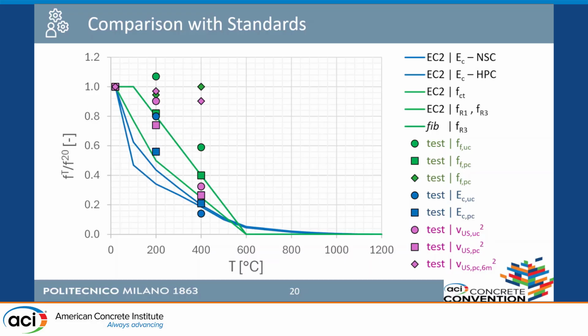I hope in the future to focus also on this aspect, because before 450 degrees C, during the curing after fire, we have a recovery thanks to the rehydration of the anhydrated particles and to the precipitation of calcium carbonate. After 450 degrees C, or even more, after 500 degrees C, we have the dehydroxylation, the decomposition of portlandite. So in the end, during the residual, during the cooling, I have a worsening, a weakening, because I have the decomposition of the solid part of the matrix. So we have to take in mind that what I said so far, if they are good news, they are valid for the range of temperature between 20 and 450 degrees C.